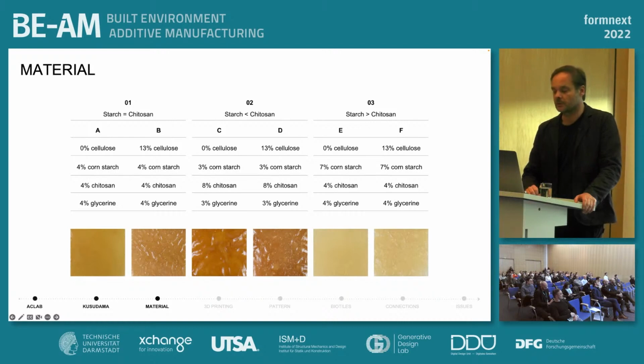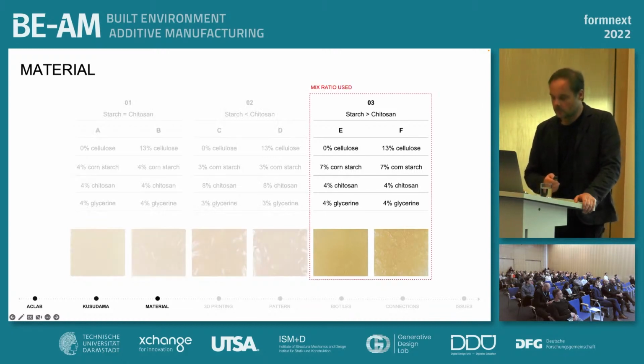This helped us to, of course, have a visual analysis of their behavior, either the color or the textures, and helped us to move on and to start to decide which mixture we'll be working on. Here on this last group, we basically were selecting mixtures with more starch and less chitosan, because we achieved a good color, good transparency, and also the fluidity of the mixture that will allow us to print or extrude to the printed extruder.